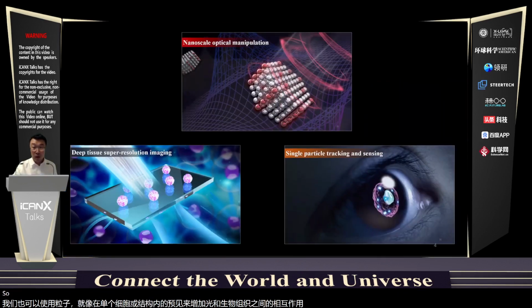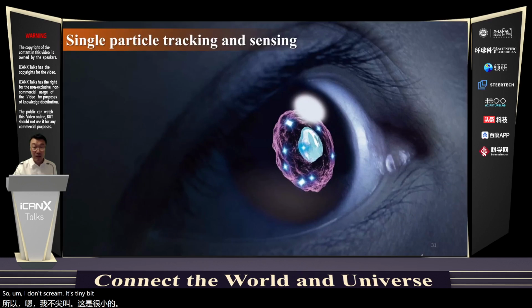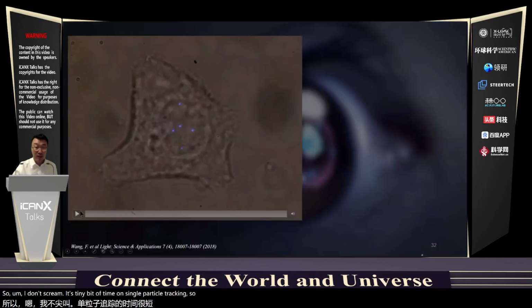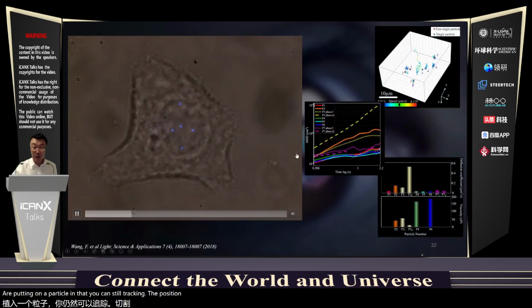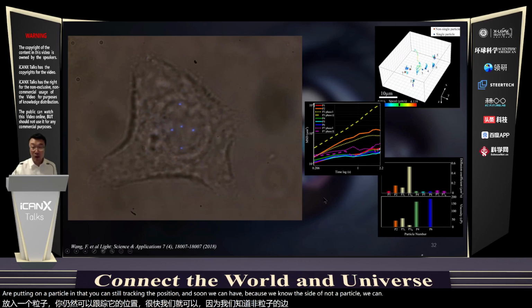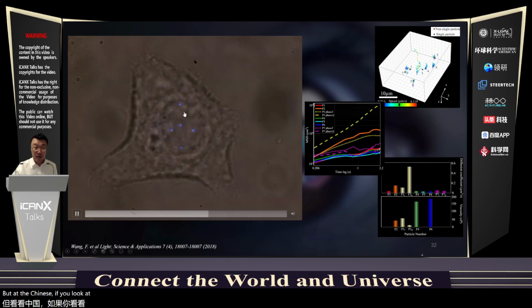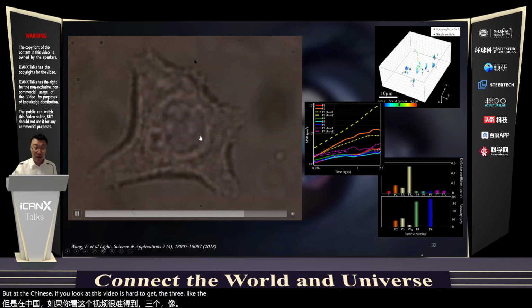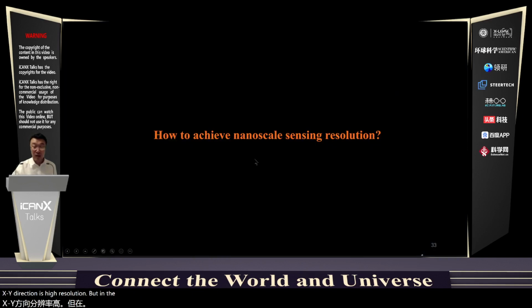So I'm going to spend a tiny bit of time on single particle tracking. Previously I developed a method to put a nanoparticle inside a given cell and track the position, and because we know the size of the nanoparticle, we can also map out the viscosity. But the challenge is, if you look at this video, the XY direction is high resolution, but in the Z direction it's hard to get nanoscale sensing resolution.